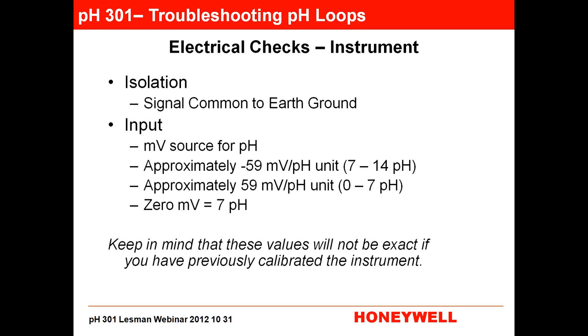And if you disconnect your pH sensor, the measure and the reference, and put the paper clip across the measure and the reference, you're now a direct connection, which means you have 0 millivolts across that terminal, and 0 millivolts is 7 pH. So when you do that with your instrument that you're having a problem with, keep in mind that